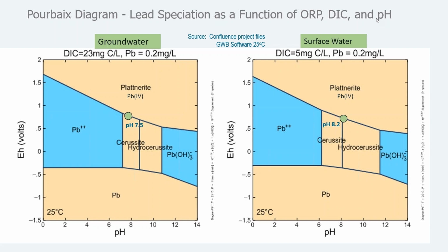Maybe everyone fell asleep when I got to the Pourbaix diagram, but no, those are the best. All right, we'll keep going here. Anyway, this diagram on this side was prepared for groundwater with a DIC of 23, and this diagram was prepared for surface water with a DIC of 5. And I think I was talking about the electrode, the ORP, where we measure the electrode potential of the water, which is pretty much controlled by chlorine residual in these waters. And again, we had high chlorine at these locations.